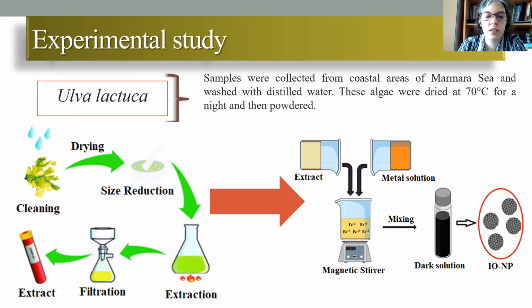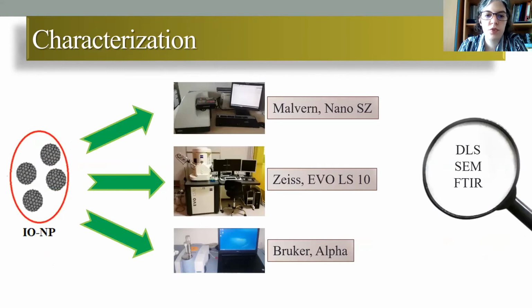After this, the algae were extracted and filtered, and the extract was mixed with a metal solution. In this study, we used ferric chloride. After mixing, we obtained a dark solution. This is one of the proofs of the chemical conversion producing iron oxide nanoparticles. As I said before, we characterized these nanoparticles by size with a Zetasizer, and we also used FTIR and SEM.